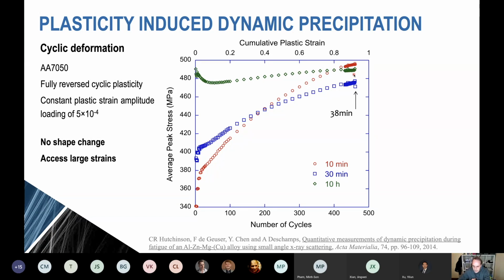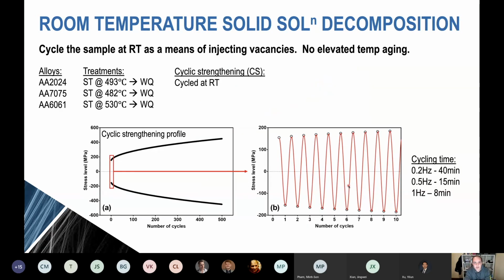And it's quite important because these alloys, when we do these heat treatments, I told you before, 150 to 200 degrees is the temperature, but a typical heat treatment would be 10 hours. And so these are very energy intensive processes, and therefore there are lots of constraints around this. So that led us to thinking about, can we use cyclic plasticity to drive room temperature decomposition of solid solutions and get properties that are interesting? Certainly we know we can drive the solid solution decomposition, but do you get anything interesting from it?